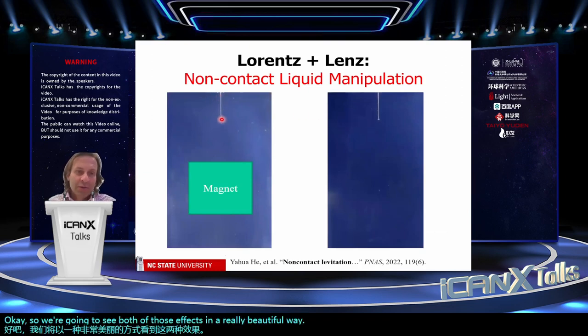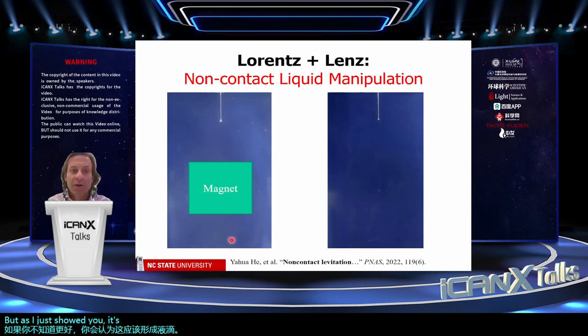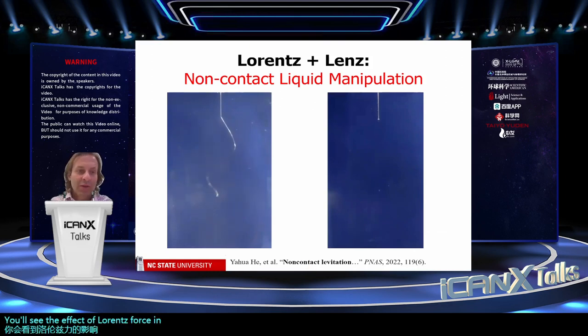Here's our nozzle. Here's the liquid metal, and we're going to pump it. And if you didn't know any better, you would think that this should form droplets. But as I just showed you, it's going to form a wire. And as that wire passes by this magnet, you'll see the effect of Lorentz force and Lenz's law. So here it goes. Lorentz force causes it to move outwards. And then Lenz's law causes it to stop at the edge of the magnet.